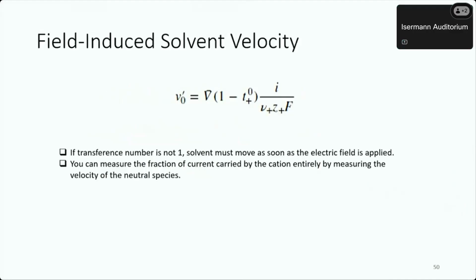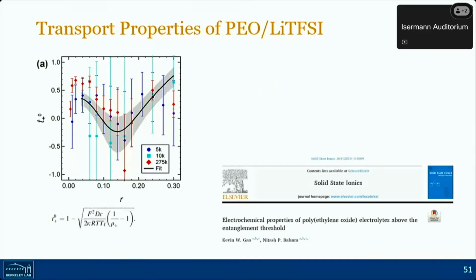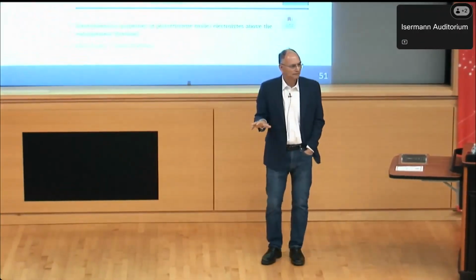And so, in fact, we have papers where we perversely just measure the solvent velocity and give the transference number, which is the fraction of the current carried by the charged species, with no problem. Well, as we were doing all this, we started measuring the transference number of this PEO. And this was a paper that caught people's attention. First of all, it's very hard to measure by classical electrochemical means. I make no excuse for this. This is probably the best measurement ever made on any electrolyte, but it has error bars that are presented for real. The best we can tell, the transference number at r equals 0.14 or so is negative.